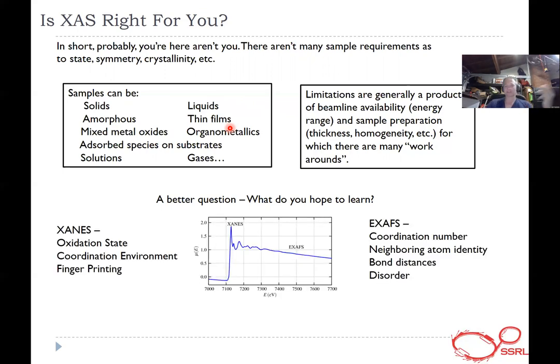So you've probably seen this twice already. Things you can learn from XANES are oxidation state, coordination environment, your ligand field. You can get fingerprinting. And from EXAFS, you can get coordination number, the identity of a neighboring atom within a certain kind of Z greater than 5 accuracy, bond distances, and disorder. You may have a crystalline sample that shows a highly ordered XRD pattern, but locally it might be disordered, and you can see the two.